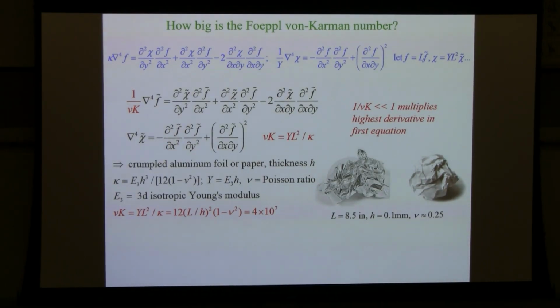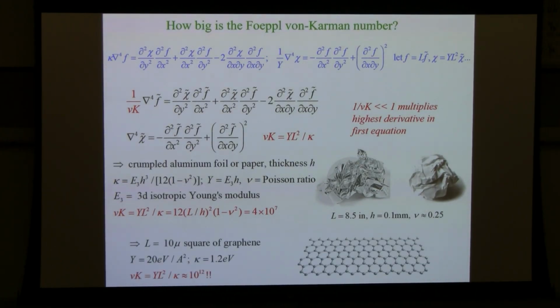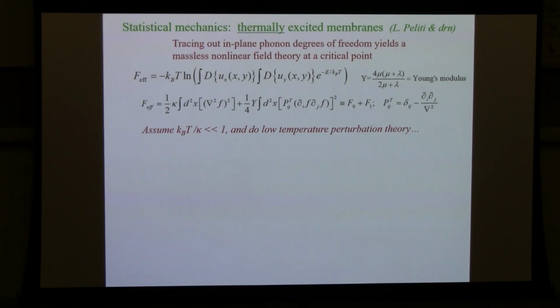And that's why figuring out the configurations of these crumpled things is a bit of a challenging problem. And if you do it for graphene, if you put in the zero temperature, our best values of the bending rigidity for graphene, which is I think about 1.2 electron volts, and this Young's modulus here, take a 10 micron square of graphene, this Foeppl-von Karman number is 10 to the 12. So good luck doing perturbation theory in powers of 10 to the 12.